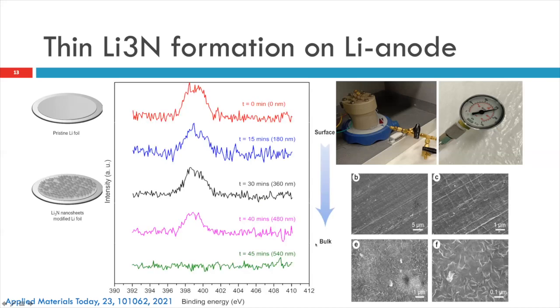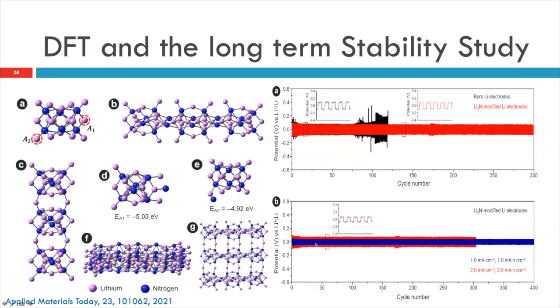Obviously, we have seen with up to 45 minutes of XPS etching that the layer we have formed is around 500 to 540 nanometers thick, a lithium nitride layer formed on the lithium. That is a very optimum thickness we have observed from several trials, and that is how we standardized our process.